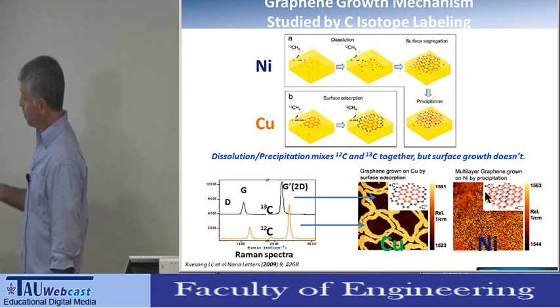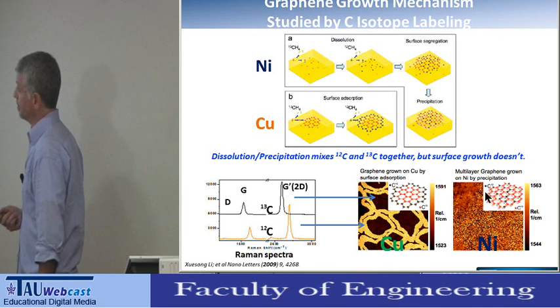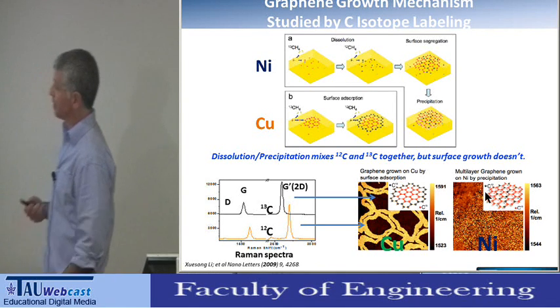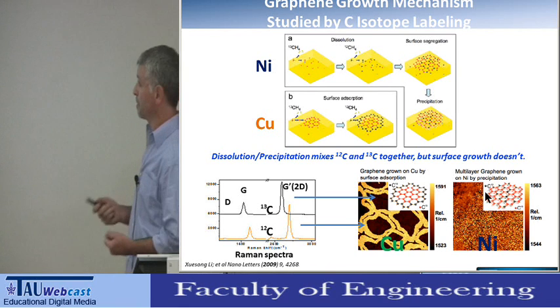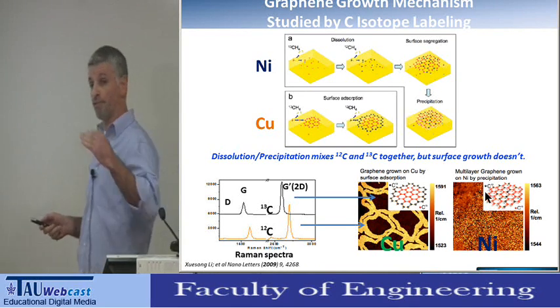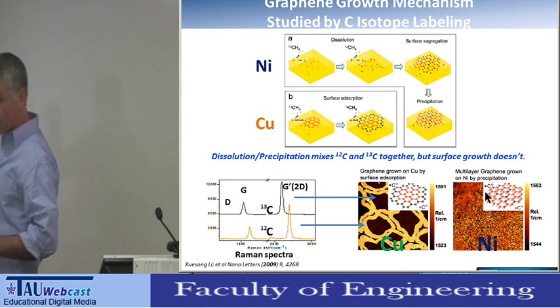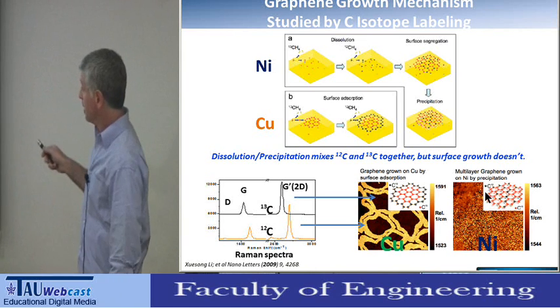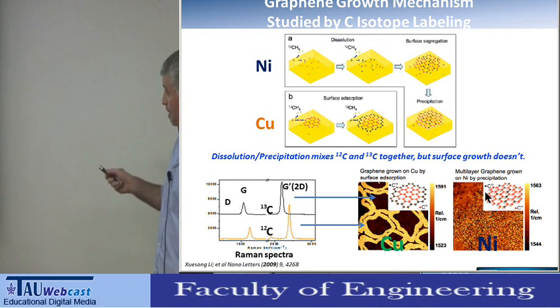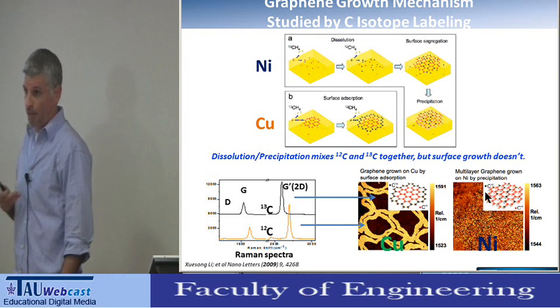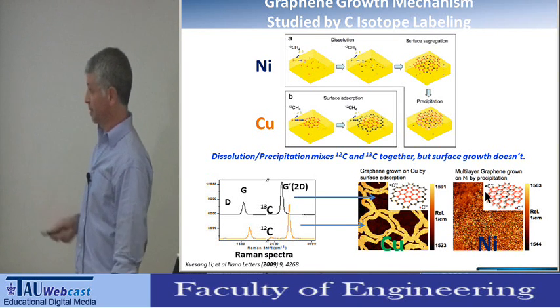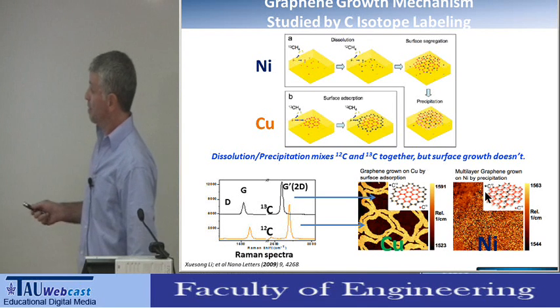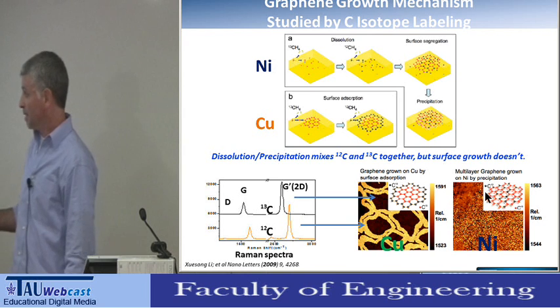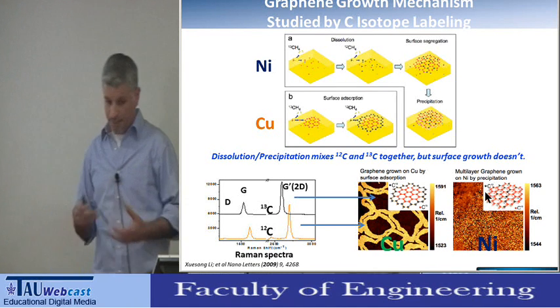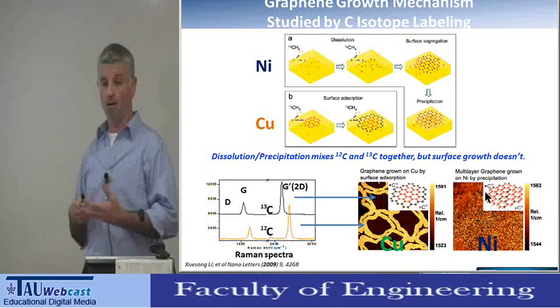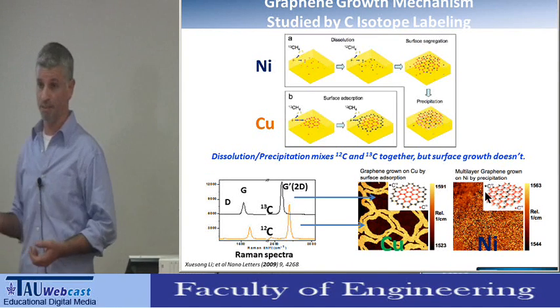So when you do this experiment on nickel, you can see that the graphene, or the few layer graphene more precisely, grows by first the decomposition of the hydrocarbon at the surface of the metal. The carbon diffuses into the bulk of the metal, and then it segregates and precipitates out when you reach supersaturation or during cooling, forming the few layer graphene. So when you do the mapping by Raman microscopy, you can see that the C12 and C13 carbon are just mixed all together, so you can't identify different regions with the different isotopes.